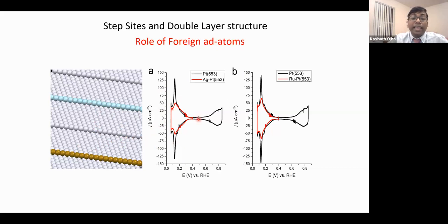So this region is again the HUPD region, the hydrogen adsorption region, and this peak is hydrogen adsorption on the step platinum sites. Now this is 553, a stepped platinum single crystal, and if you add silver on the step sites, then you block those step sites, so you don't adsorb hydrogen there, so that peak is minimized, you don't see the peak anymore. But the rest of the HUPD region remains the same, because the rest of the HUPD region is coming from hydrogen adsorption on the terrace atoms. So terraces are fine, only step sites are blocked.